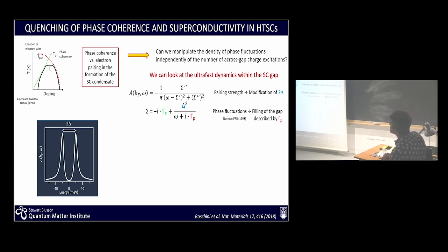Well, if we look in a region where we have a superconducting gap, here is the chemical potential, and we are below Tc. Now we find two peaks in the spectral function, one below and one above the chemical potential, and the difference between the two of them is 2 delta, the superconducting pairing. And now the question is, if phase coherence, if we go and pump the system, and now we can tell the difference whether or not delta or gamma are dominating the effect.